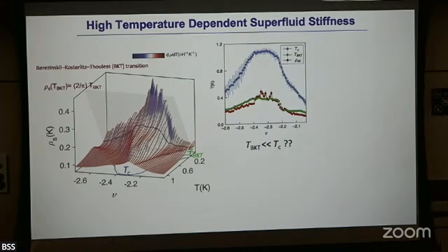Yes, right. So Tc, how did we measure Tc? Basically we measure, say, IV. This is V. So we send the current and measure the voltage. In the superconducting state, it's completely zero voltage, and at some point it starts to rise. Then in a 2D superconductor, there's always some sort of power law behavior.